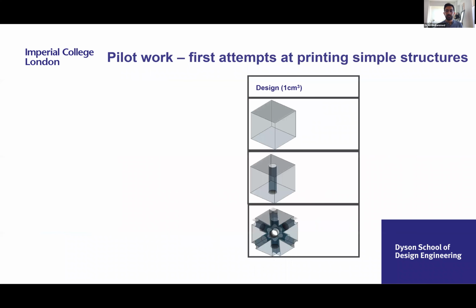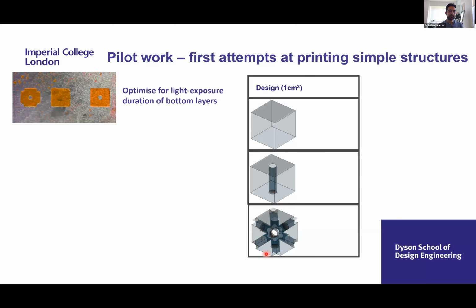The next step was to attempt to 3D print using our 3D printer, g-DLP. We designed some basic 1 centimeter cube structures with a solid block, a single channel, and a 7-strut 2.5 millimeter lattice, and attempted to print using the base formulation that we generated. The first attempts weren't very successful. We would only get one slice of the structure on the print platform, and the rest would fail.